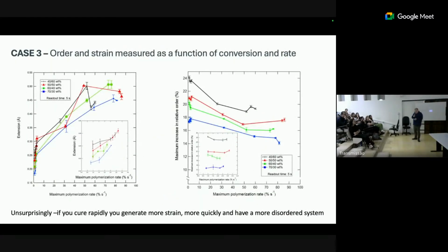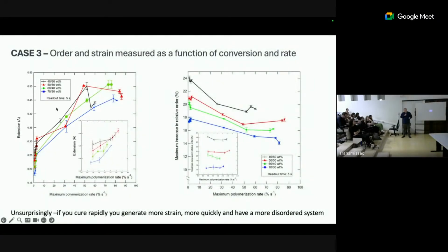And this is what we find. So this is just the summary of what we understood. What we found is that if we ramp up the polymerization rate, which is down here on this axis, and we look at how initially the monomer extends to become a polymer, depending on the rate of cure, and what we're looking at in the different colors are systems that have different viscosities, but also different photoinitiators, we end up with a difference in initial strain.